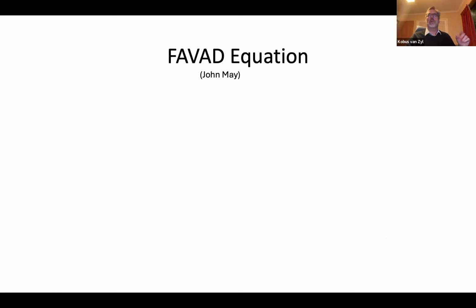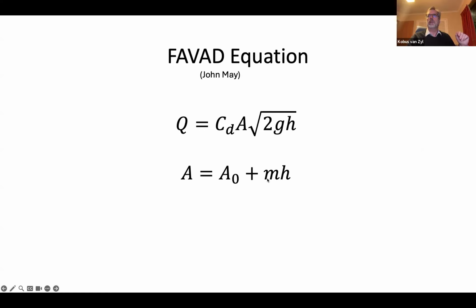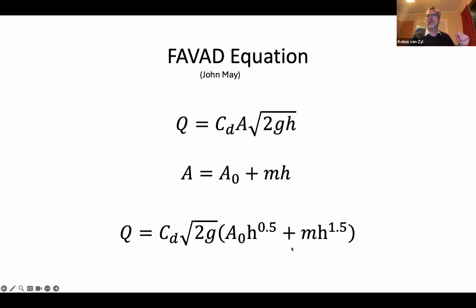So that brings us to the FAVAD equation, which all of you will have heard about or know. John May famously introduced that. This is the orifice equation, which describes the leak: the flow rate through an orifice is a function of the square root of the pressure, times the area. But if the area is not fixed, but is a linear function, so it's an initial area plus the slope, we call it the head area slope, times the pressure, then we get to this, which is called the FAVAD equation. And this has two terms: h, the pressure to the power 0.5, and a pressure to the power 1.5. This is what John May pointed out, and it explains why the N1 leakage exponent can be between 0.5 and 1.5. This applies to individual leaks, and with our understanding of material science, we can actually predict for a given leak what N1 will be.